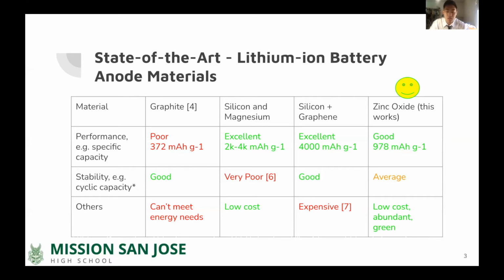Finding an environmentally sustainable and cheap option for battery materials that can still provide the required specific capacity, electric conductivity, and the lithium-ion transfer rate is a worthwhile goal. Metal oxides usually meet these criteria very well. We turn to zinc oxide as an option because of its abundance in the environment, its affordability, and its high theoretical capacity. There are many different types of anode material combinations with zinc oxide, each with its own advantages and drawbacks. Generally, zinc oxide anodes have a relatively high theoretical capacity of 978 milliamp hours per gram. Though not as high as silicon, it's still decent to consider for further research.